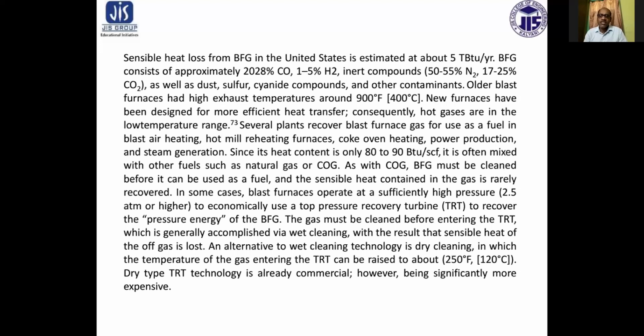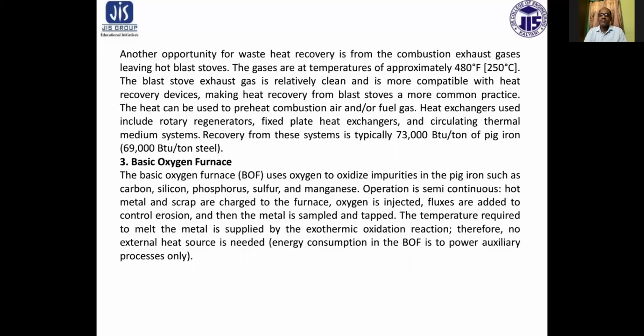Dry type TRT technology, that is top pressure recovery turbine, is already commercial, however it is a significantly expensive device. Another opportunity for waste heat recovery is the combustion exhaust gases leaving the hot blast stove. The gases are at a temperature of around 250 degrees centigrade. The blast stove exhaust gas is relatively clean and more compatible with the heat recovery device, making heat recovery from blast stove a more common practice.